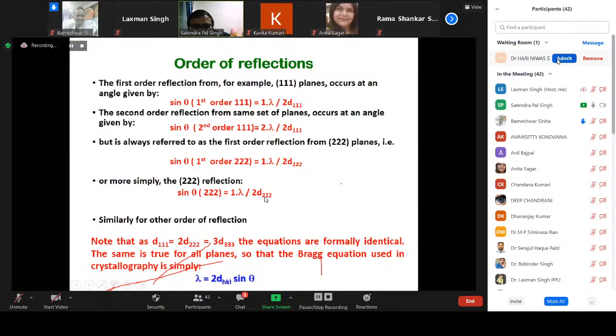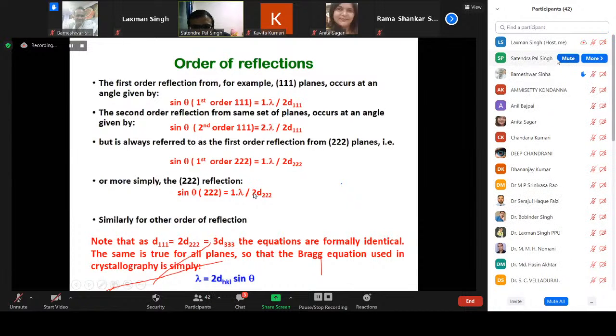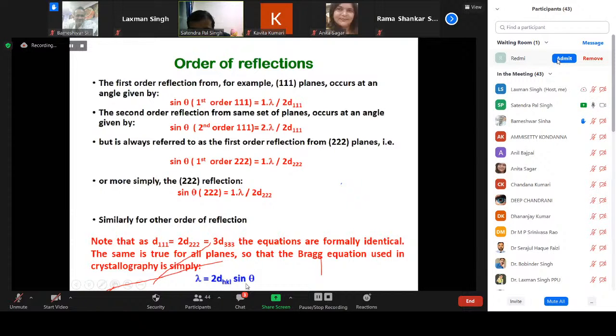So instead of using n, we simply use Bragg's law as lambda equals 2d sin theta, not n lambda. In place of d, we use the terminology d HKL, and this d HKL is related to the lattice parameter and the HKL values. So Bragg's law is generally used in this form: lambda equals 2 d HKL sin theta.